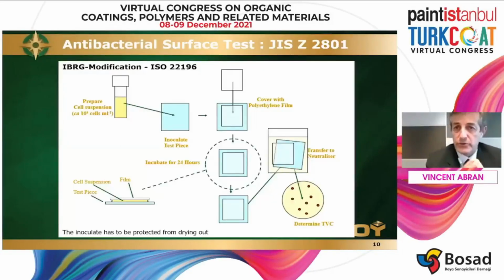Now, if we focus on the JIS Z 2801 standard, you will see the concept, let me now use my laser pointer. So we have a suspension of 10 to the 5th bacteria cells per milliliter, and we have Escherichia coli on one side and Staphylococcus aureus on the other side. Two different types of bacteria. We have a test piece of coating, applied on filter paper to a certain thickness. And then we apply the solution on the coating, one for each type of bacteria. And then we apply a polyethylene film to maintain the solution onto the surface for 24 hours. We incubate the test specimen plus the solution for 24 hours.